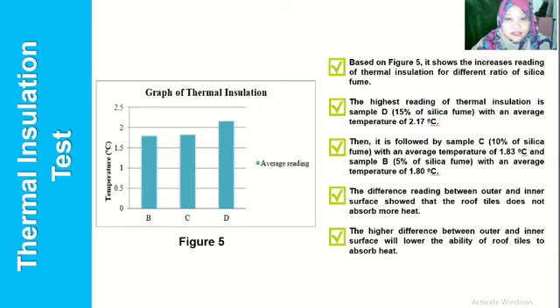Okay, let's proceed to the last test for this research, which is the thermal insulation test. Based on figure 5, it shows the increasing reading of thermal insulation for different ratios of silica fume. The highest reading of thermal insulation is sample D, which is 15% of silica fume, with an average temperature of 2.17 degrees Celsius. Then it is followed by sample C, which is 10% of silica fume, with an average temperature of 1.83 degrees Celsius, and sample B, which is 5% of silica fume, with an average temperature of 1.8 degrees Celsius. The difference in reading between outer and inner surface shows that the roof tile does not absorb more heat. The higher difference between outer and inner surface will lower the ability of roof tiles to absorb heat.